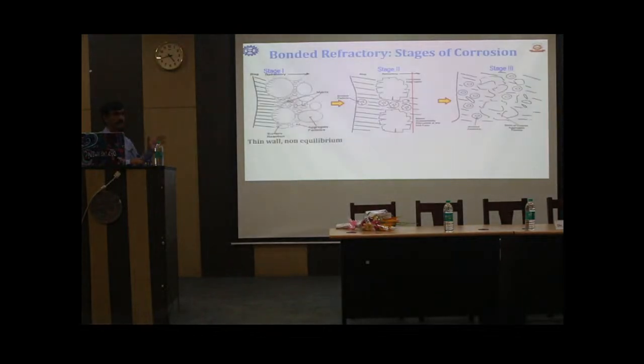For bonded refractory, there are three stages. With the bonded structure, there are bigger grains bonded with the fine matrix. Initially the liquid just acts on the fine matrix, dissolves it, and corrodes the surface of the grains. This is the first stage: only the fine matrix is attacked by the liquid. In the second stage, the smaller aggregate and the bigger aggregate are corroded too. Then in the third stage, once the bond matrix is dissolved and some of the grains are corroded, it just wears out. So effectively it is not penetration, effectively you just wear out the samples.